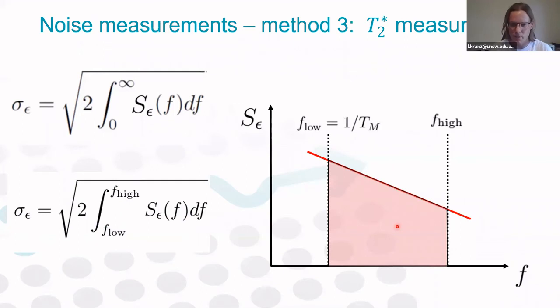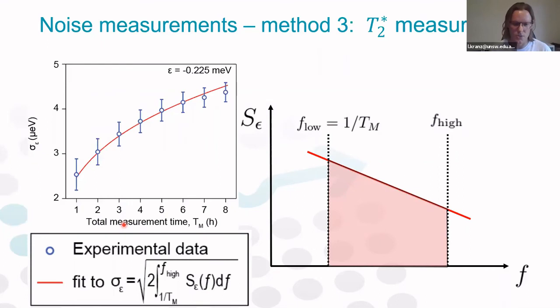However, for the experiments, we can limit our considerations to a certain frequency range. In particular, the lowest frequency that can couple to your experiment can be written as 1/total measurement time. So we can put finite bounds on this integral now. Using this equation and assuming that the noise has a power law spectrum, we actually get a really good fit to our data. This tells us that the noise causing fluctuations in the detuning between our two qubits comes from an ensemble of two-level fluctuators causing power law frequency noise.